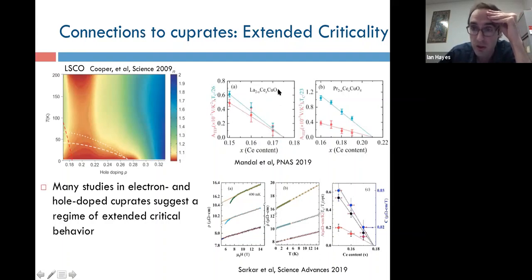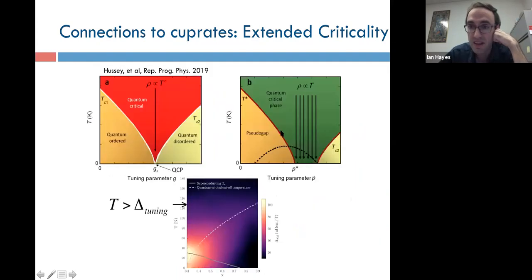Electron-doped cuprates, where you can measure the low temperature resistance fairly directly, also show a T-linear behavior that vanishes near the overdoped side. And those same films also show a logarithmic upturn at low temperatures, that's often characteristic of quantum critical systems, that diminishes and vanishes at the same point where superconductivity does on the overdoped side. And this is nicely laid out in a paper by Nigel that contrasts the way criticality seems to emerge in pnictides and cuprates, whereas in the cuprates, you seem to have an extended region of some sort of critical behavior going up to the edge of the superconducting dome.